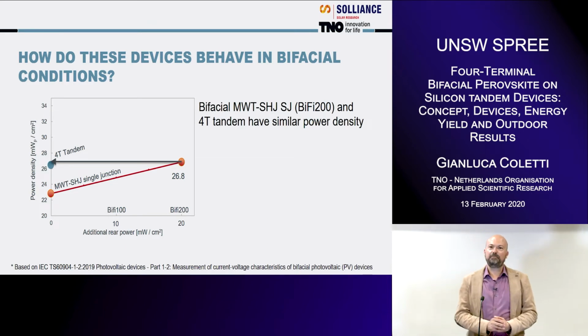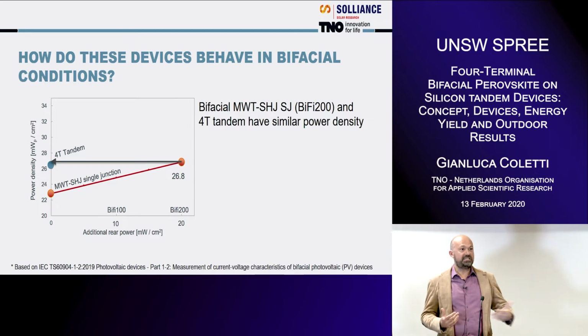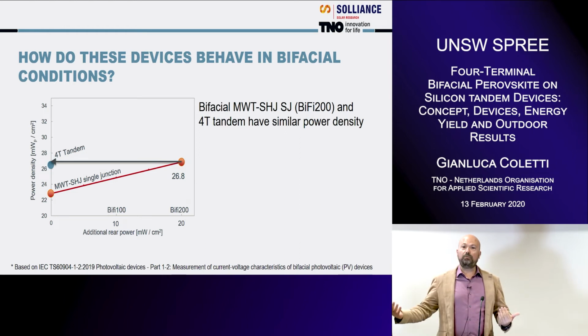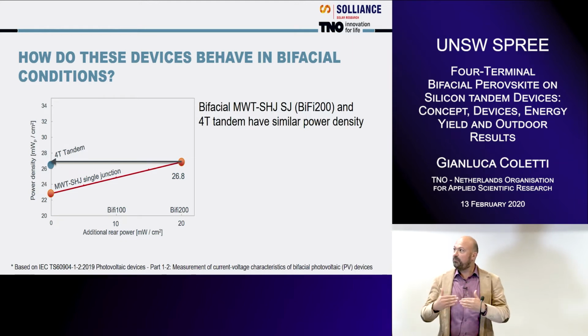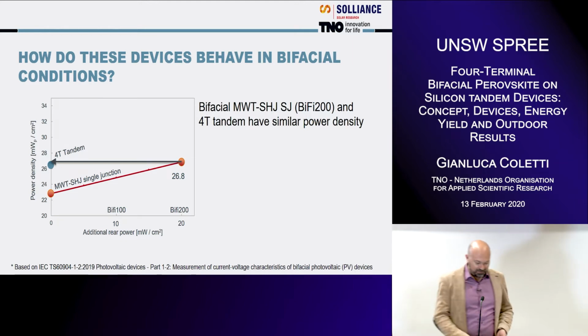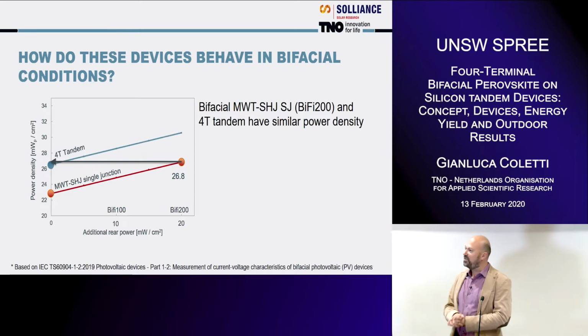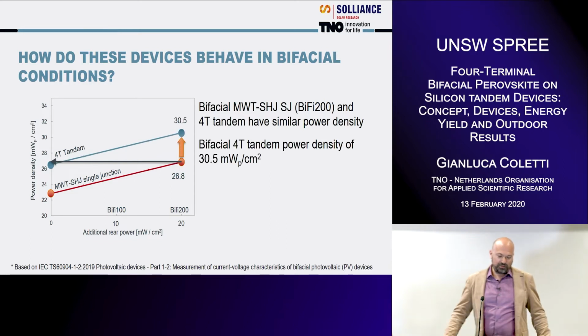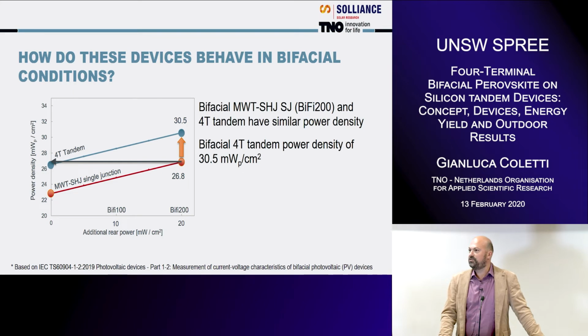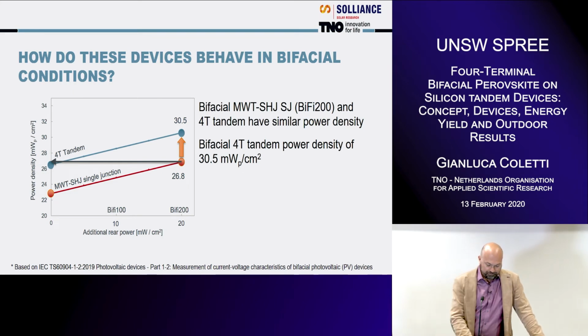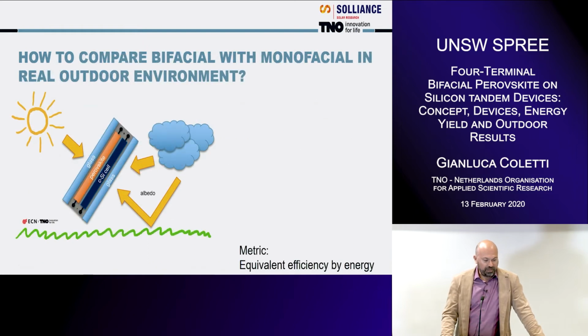So essentially you make a device that has more than 4% absolute gain with respect to the single junction, but when you compare with a bifacial device, single junction has the same power. So why do you do that? You do that because you can have it bifacial too. And then you end up with a power density of over 30 milliwatt per square centimeter. And this is the interesting part, right? So let's move to next.